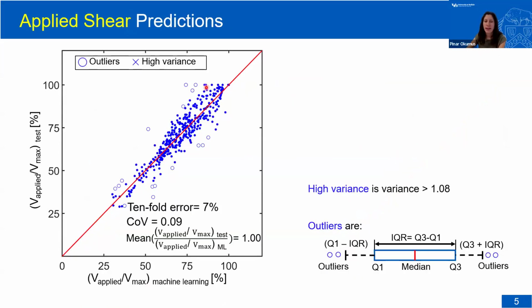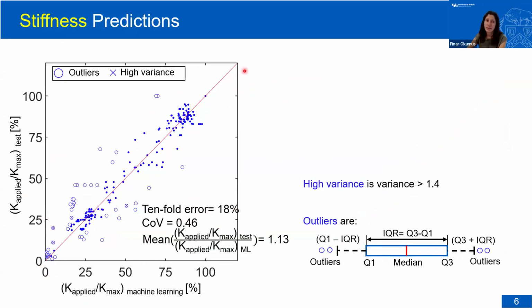For applied shear, again, same type of plot. So this is that applied shear corresponding to a crack normalized by shear strength. Horizontal axis is machine learning. We have pretty good predictions, really good error, and a really nice coefficient of variation. And then this is the stiffness predictions. You can see, I will say 18% is acceptable, but you see a large scatter, and then the small size of the data is also apparent from this plot. So this is our stiffness divided by initial stiffness predictions.